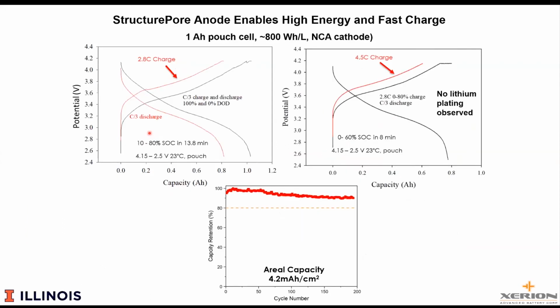And so now this is a little bit on fast charging. And so this is now fast charging at 4.5 C. And so there's no lithium plating observed, even though this is being charged now in the order of 12 to 15 minutes. We've done some work up to 6 C, so that's about 10-minute charge. And that's really because fundamentally the lithium likes to be in the silicon.